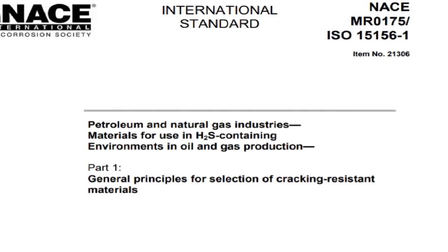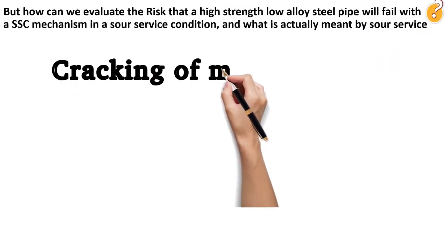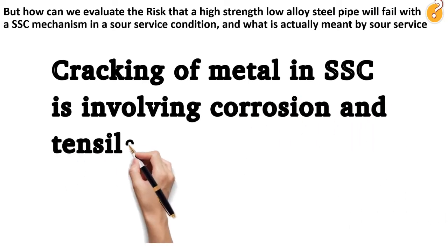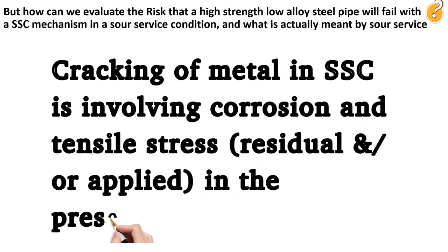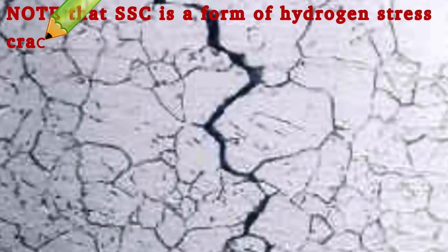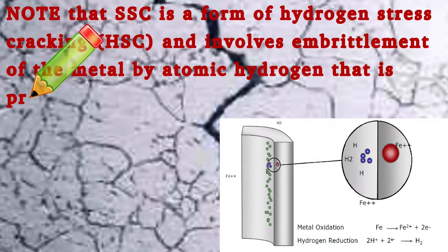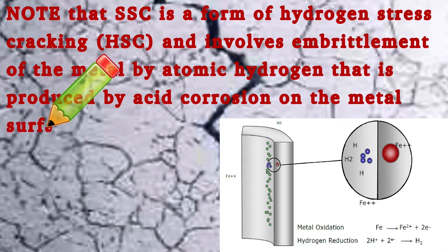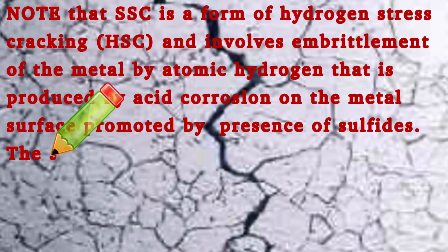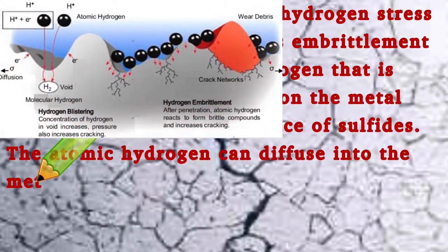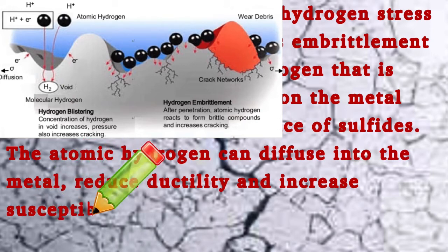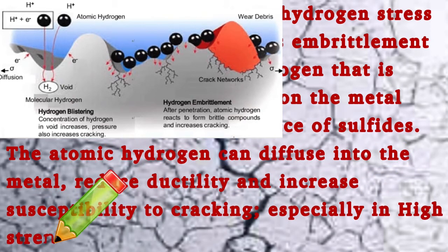And as per the standards covering these types of services, like NACE MR0175 and ISO 15156, SSC is the cracking of metal involving corrosion and tensile stress, residual and/or applied, in the presence of water and H2S. Note that SSC is a form of hydrogen stress cracking, HSC, and involves embrittlement of the metal by atomic hydrogen that is produced by acid corrosion on the metal surface, promoted by the presence of sulfides. The atomic hydrogen can diffuse into the metal, reduce ductility and increase susceptibility to cracking, especially in high-strength metallic materials.